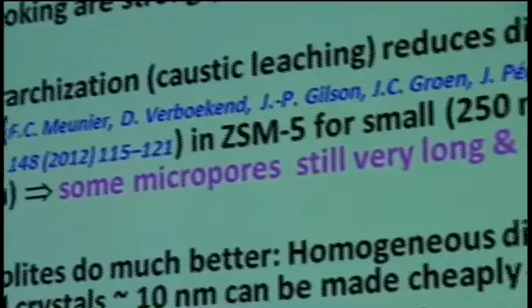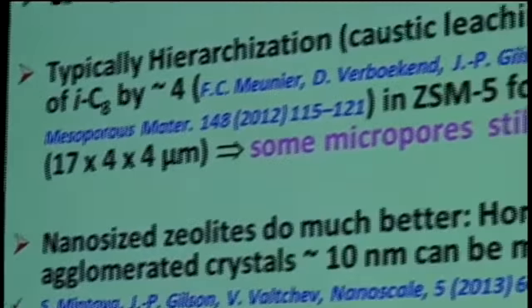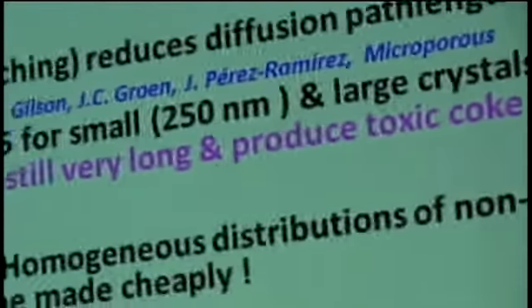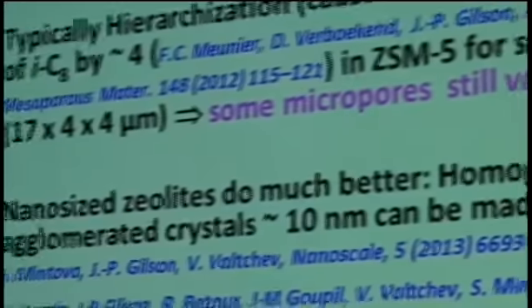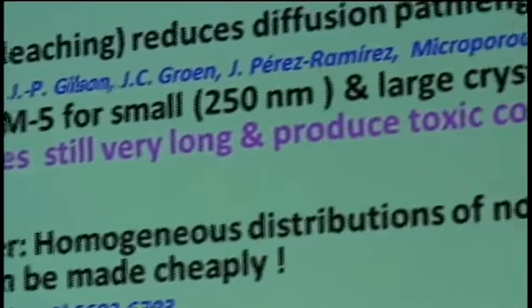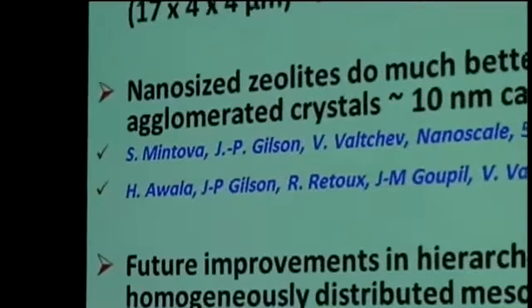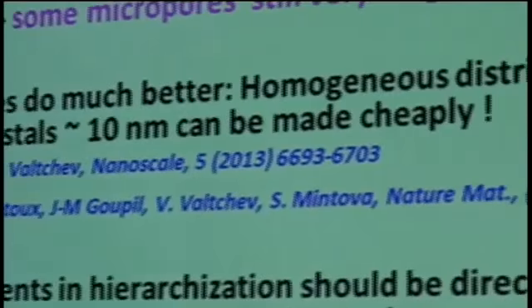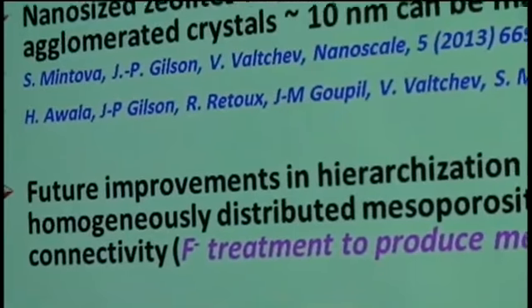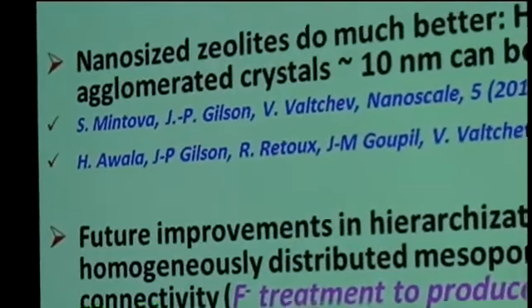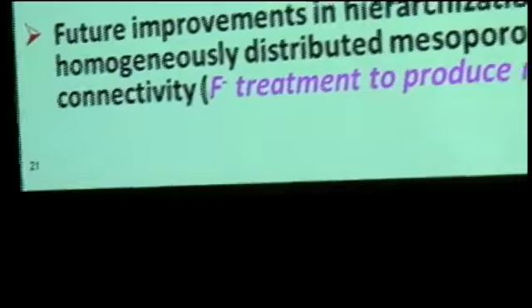Coking and decoking are strongly influenced by diffusion, and here again you see a difference. I can advise you to have a look at this paper. This is a collaboration with Fred Meunier, when he was still in Caen, now he's in Lyon, and again with Javier Pérez-Ramírez. By diffusion measurements we tried to backtrack to the diffusion path length that was present in the parent zeolite and the treated zeolite, and basically in ZSM-5 treated in the conditions of the current study, we were cutting the average diffusion path length by a factor of 4 by hierarchization. You do much better with nano-sized crystals because you cut that by at least one order of magnitude.